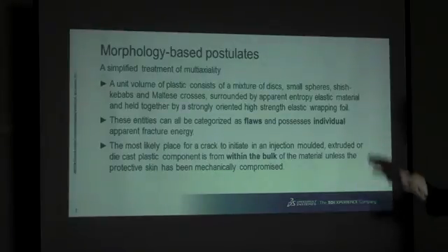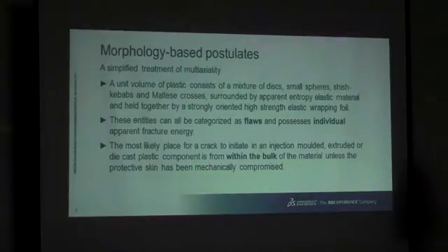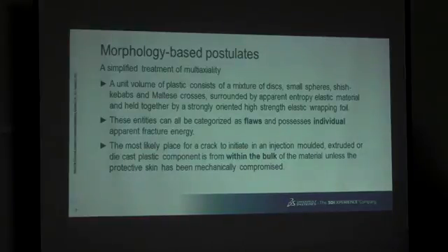The most likely place for any crack to initiate in an injection molded component is never on the surface, unless you compromise it. Unless you scratch the surface, you do something to it, the cracks will never start on the surface. They will start from within. That's the biggest problem. And a lot more notable authors than me have concluded so over the years. So it's something I've just happened to see for myself to the same extent.